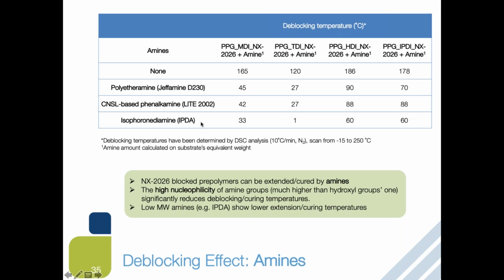Now, as soon as we introduce amine in those systems, there is a significant reduction in the deblocking temperature, especially with MDI and TDI. You can see deblocking temperature being 1 degree C with the IPDA as a deblocking agent. So basically, amines are much more effective deblocking agents because of their high nucleophilicity in comparison to polyol. And we also noticed that low molecular weight amines are a more effective solution to lower the deblocking temperature.